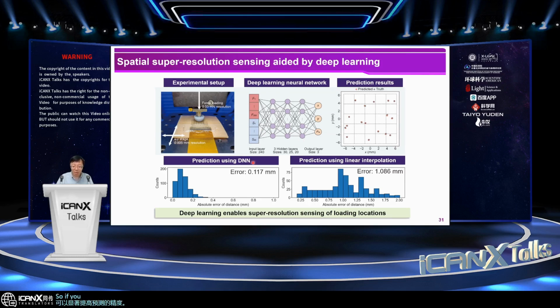So if you look at the results on the bottom, you can see a substantial enhancement of the loading position from around 1.086 millimeter to 0.117 millimeter in comparison to the case of linear interpolation. So this is a ninefold enhancement of the loading position, which is very effective.